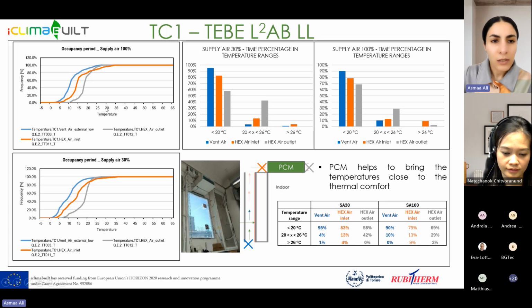And this was done in supply air mode in winter, and you see the PCM was able to bring the temperature even closer to the comfort zone, which is close to 20 here at the set point. So here is a representation of how much the PCM can contribute to this.